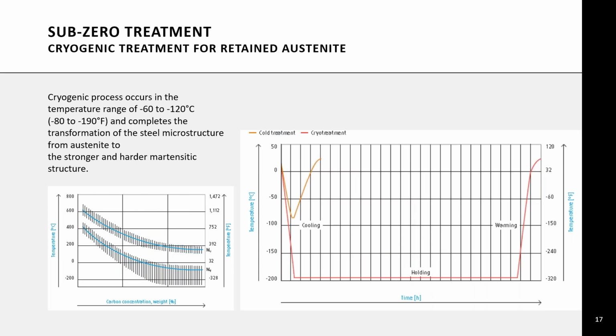As an isolated cryogenic step, special freezers can easily be integrated into manufacturers' existing heat treatment processes, typically working at temperatures ranging from -60 C to -180. These treatments take between 4 and 72 hours, depending on the goal of the process. The transformation of retained austenite to martensite can be achieved at a range between -60 C and -120 C, and a dwell time of about 1 to 4 hours, depending on the cross-section of the materials. Applying cooler temperatures between -120 and -180 with longer dwell times will also support precipitation of fine carbides, with improved wear resistance of metal parts.